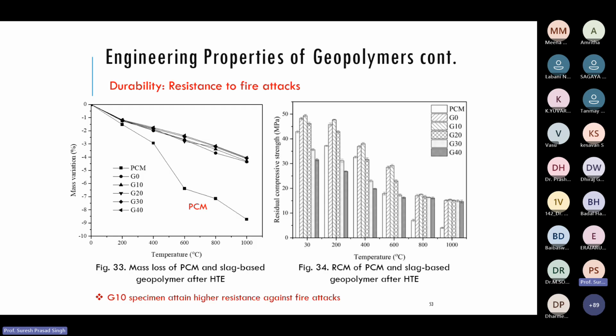So this is the fire attack. This is the mass variation, mass loss of the normal Portland cement mortar. You see there is a lot of loss in mass after exposure to high temperature. We increased the temperature at a rate of 5 degrees per minute to 200, 400, 600, 800 or up to 1000. Then we kept it for 1 hour at the elevated temperature, then gradually reduced it.